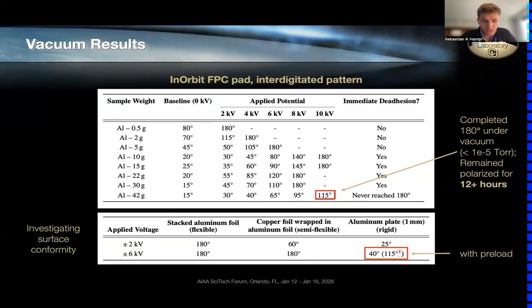As you can see, the 42-gram sample could not complete a full rotation in atmospheric conditions. This is why we repeated the test under vacuum conditions and only applied 8 kilovolts in this case. And the sample rotated to 180 degrees without any problems, showing a stronger electroadhesion force. And interestingly, after turning off the voltage, it stayed on for 12 plus hours, while previously lighter samples had fallen off almost immediately after turning off the force.